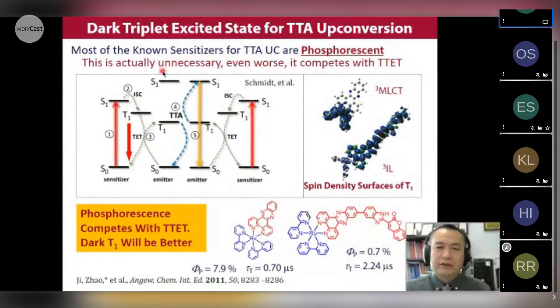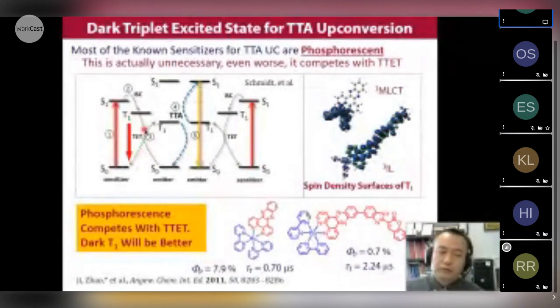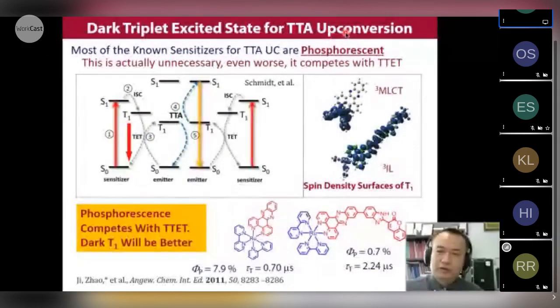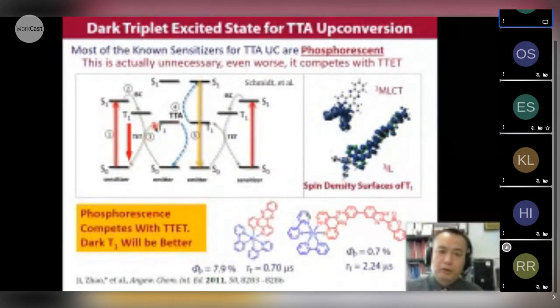Another new idea we studied for the upconversion is using a dark triplet state. So normally the photosensitizer used for upconversion is with strong phosphorescence. So actually the phosphorescence is competing with the intermolecular energy transfer. So we don't need the T1 state of the photosensitizer to be phosphorescent. So therefore we prepared a complex which is almost non-phosphorescent compared to the model one.